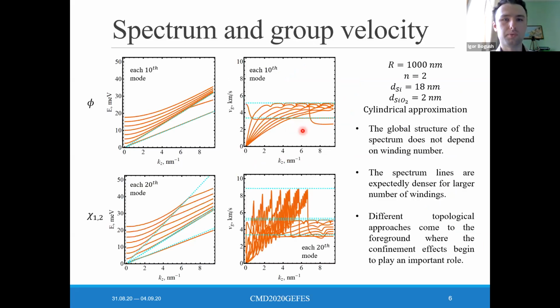Here's an example of the spectrum and group velocity that we got for the nanostructure with radius equal to 1 micrometer and 2 windings. The width of the winding is equal to 20 nanometers. Here we used the cylindrical approximation, and phi is a transversal mode, and chi is a mixed longitudinal transversal mode.